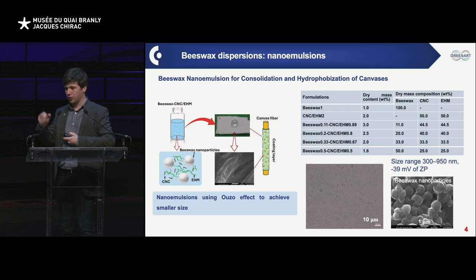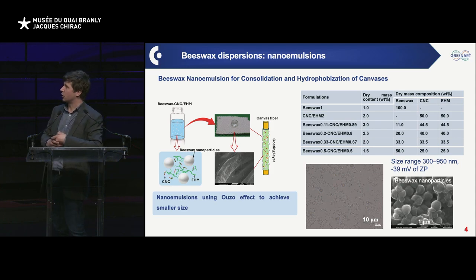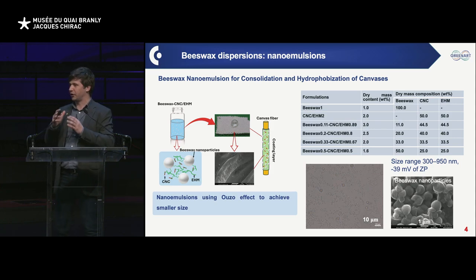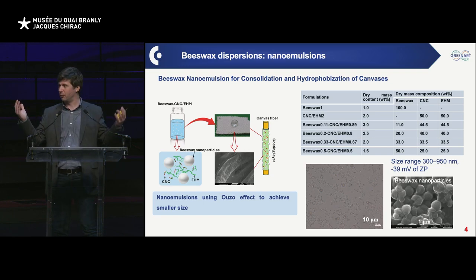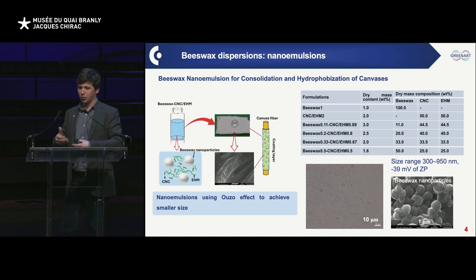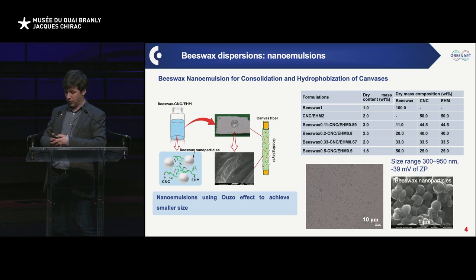That's very small particles. You can see on that SEM picture that they are in the micron size or even smaller than micron size on this micrograph, essentially. And eventually, by using the same type of formulation, we have something interesting. But in that case, the cellulose nanocrystals are not adsorbed by definition on the surface. It's a free-floating element, as EHM is. And we have other type of interaction at play.